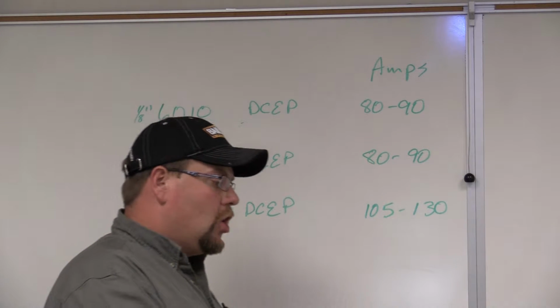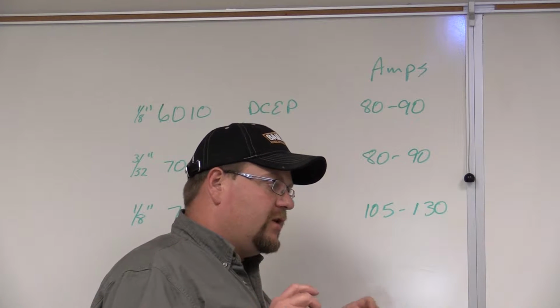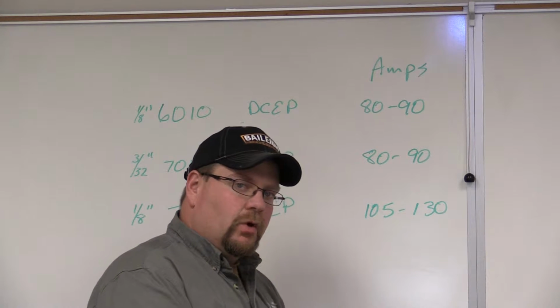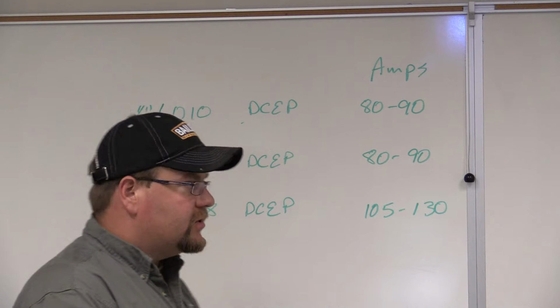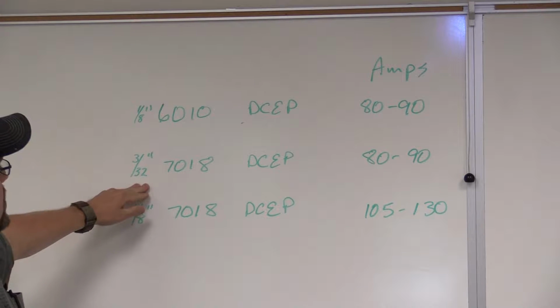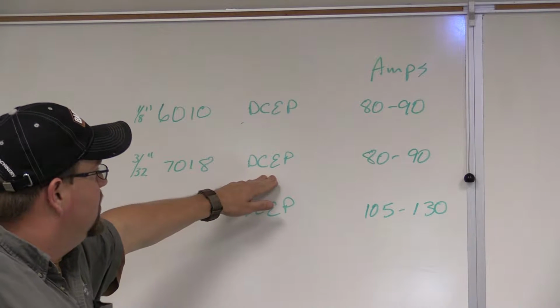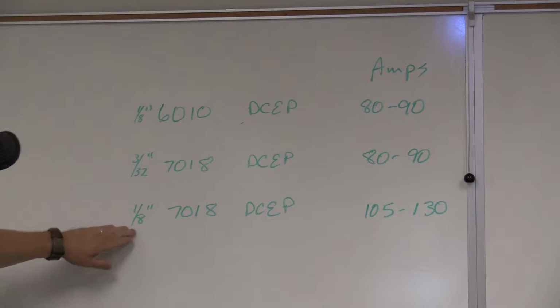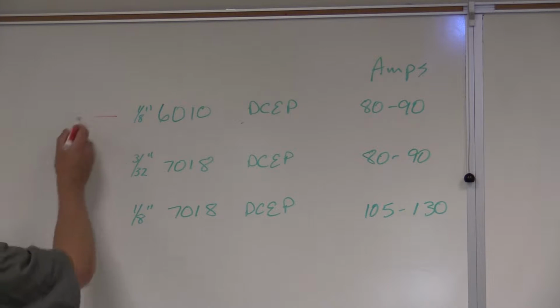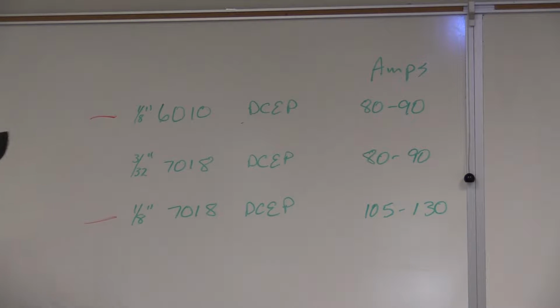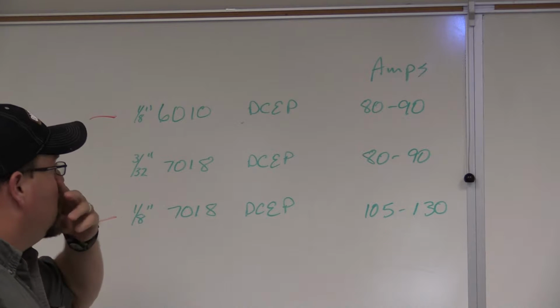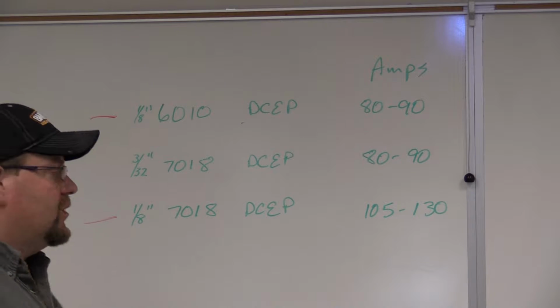But if you get too much higher than this, it creates a very volatile arc. And it actually creates more of an issue where it's a turbulent flow and you're pulling moisture in and porosity within your weld if you get too high amperage. Okay? The 3/32 diameter 7018 low hydrogen electrode, DC electrode positive, 80 to 90 amps, roughly the same. Now here's what you're going to be starting out with. You're going to be starting out with 6010 1/8 inch and 7018 1/8 inch. I want you to get used to those two sizes of electrodes first, and then we can move on to exploring with some 3/32 and so forth, okay?